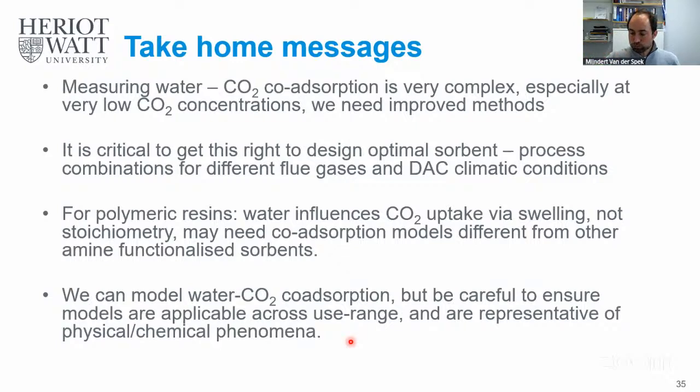We have a question from Clinton Obang Manu. How does the pre-humidification affect the chemisorbed products on your sample? Yeah, so it doesn't. We see the exact same chemisorbed product, ammonium carbamate, under dry and humidified conditions, and that is contrary to what the literature has always said. So the literature, at least for our material, is wrong.